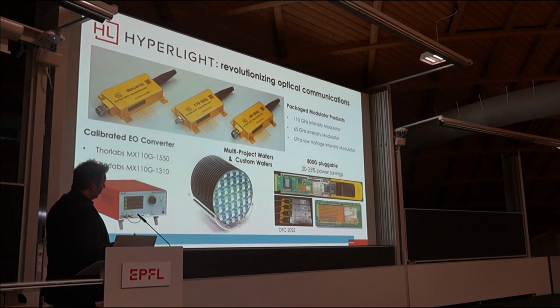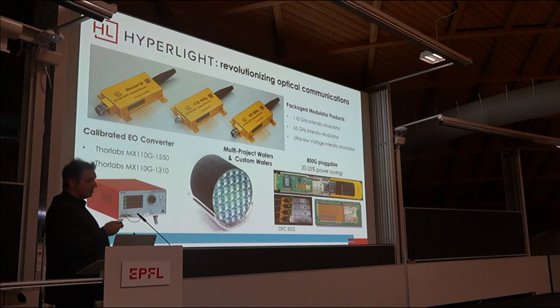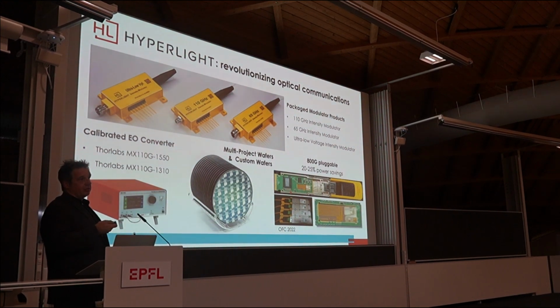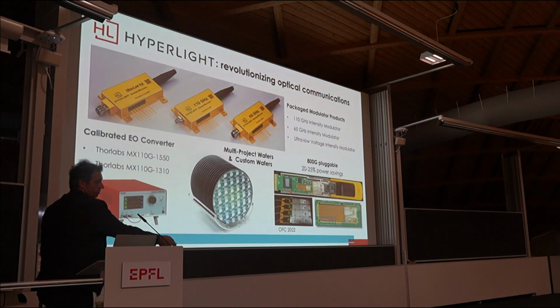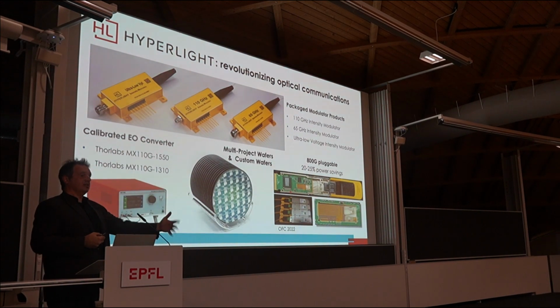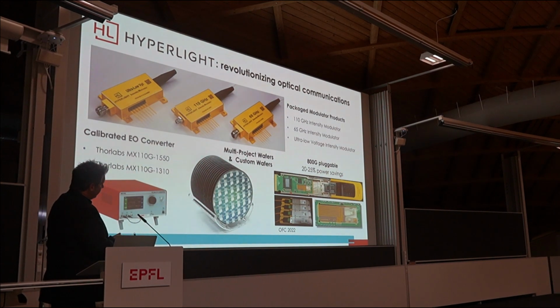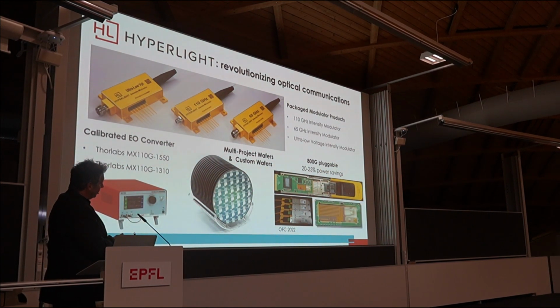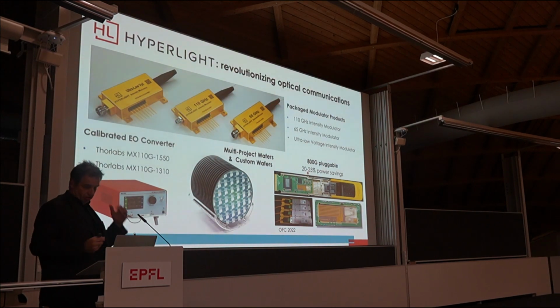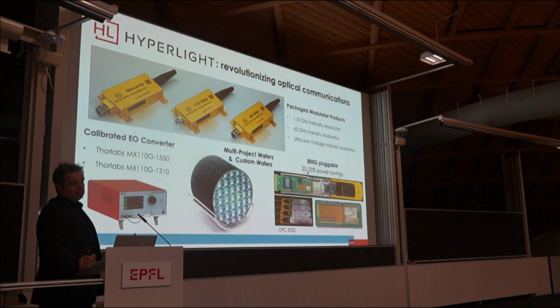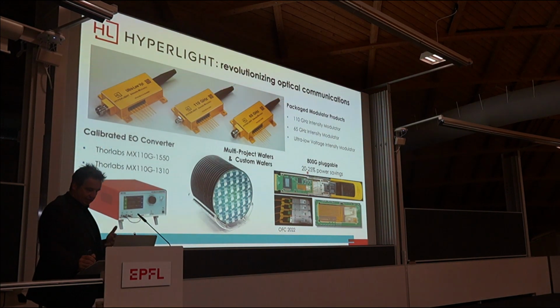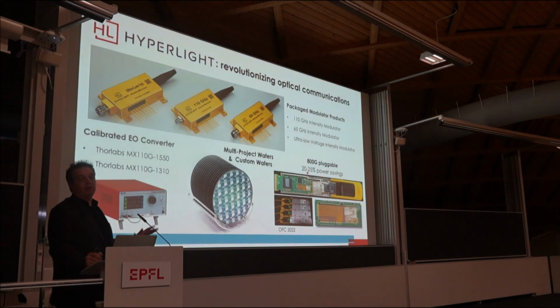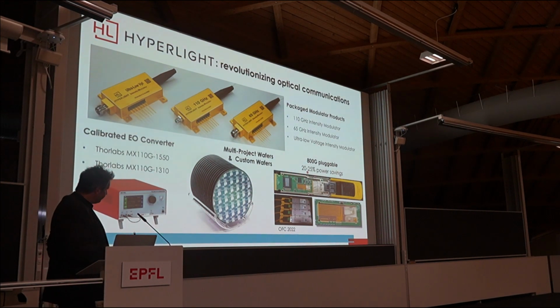At the OFC conference a few years ago, there was a demonstration discussed in a panel presentation by Arista Networks. These are pluggables, devices, transceivers that convert signals from the electrical domain to the optical domain. So basically you put this thing into a computer rack, and on one end you have electrical 1s and 0s, on the other, optical 1s and 0s. By replacing the silicon photonics chip with a lithium niobate photonics chip, as shown here, they were able to reduce power consumption tremendously, which is a big deal in this community. Because, as you may know, data centers and all the infrastructure around AI are burning tons of power. And that's one of the big problems.